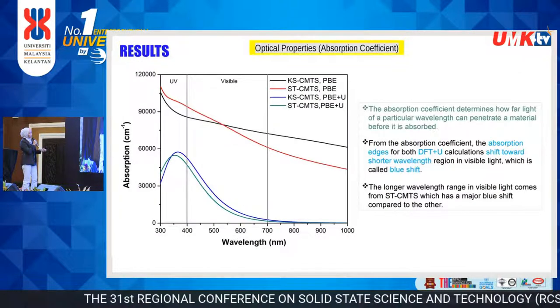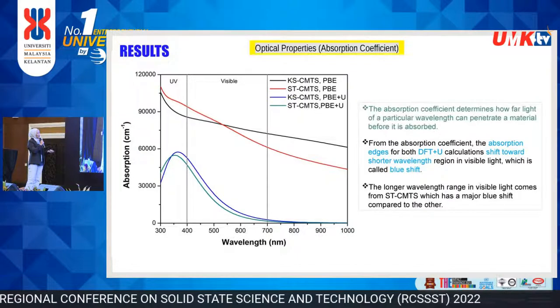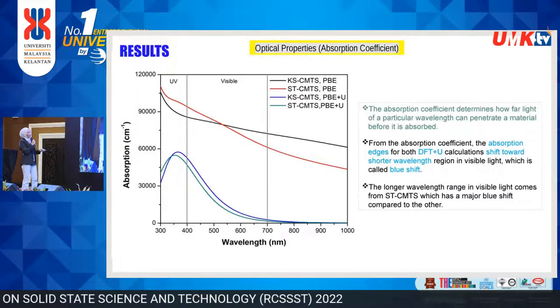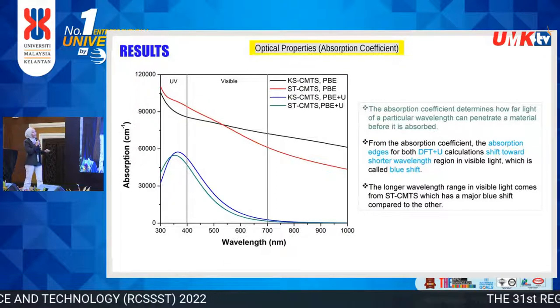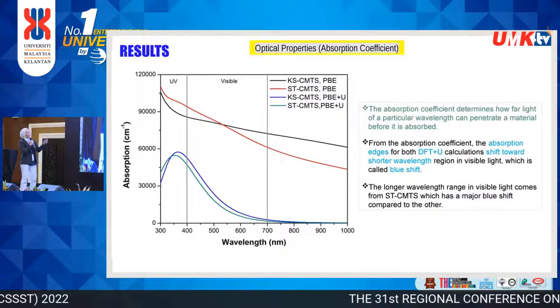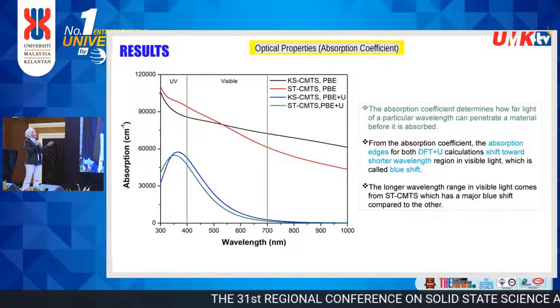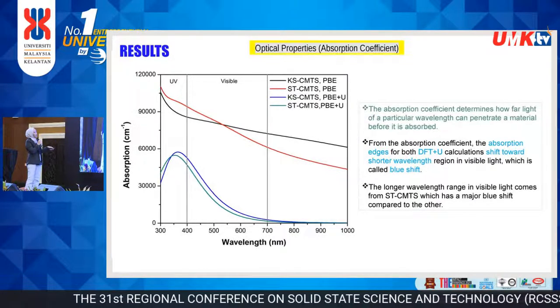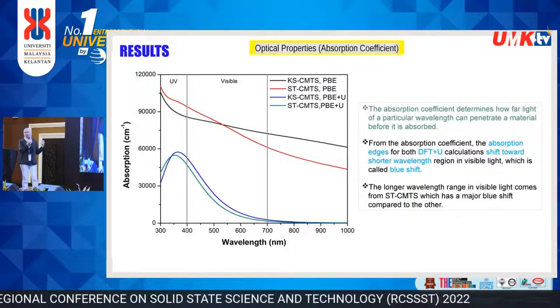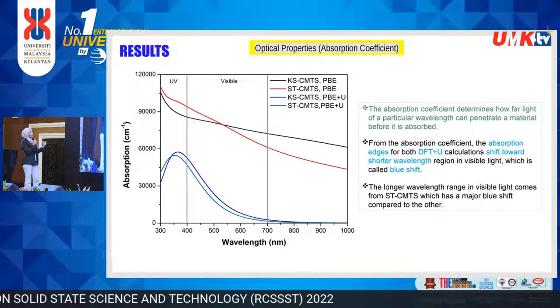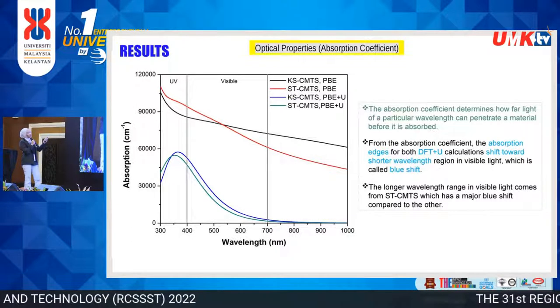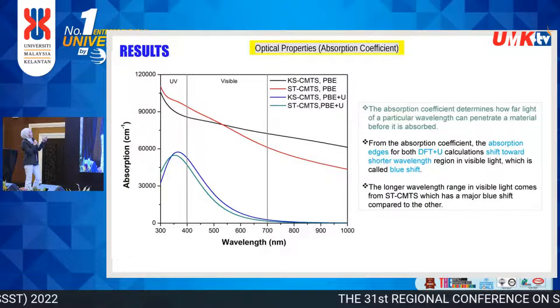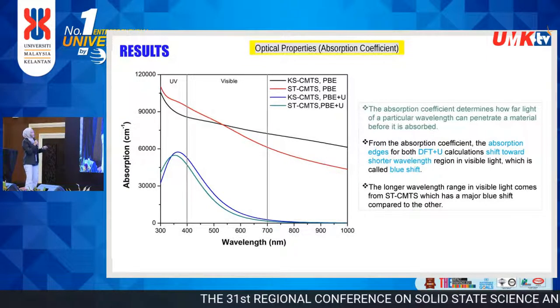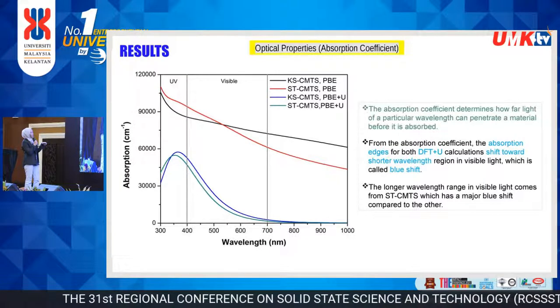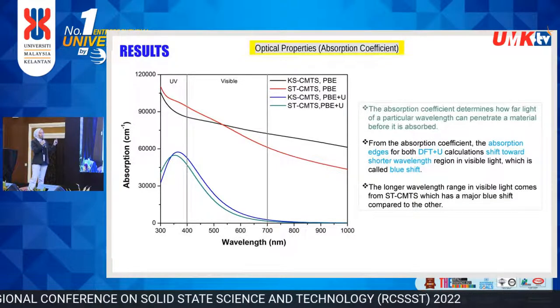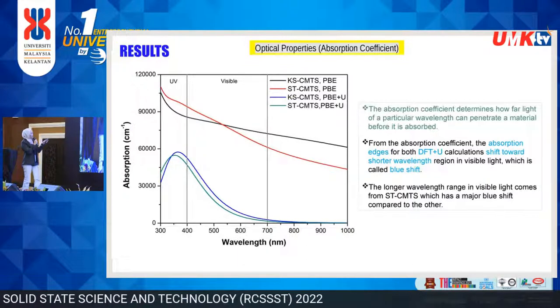Okay, this is the absorption coefficient, which determines how far light of a particular wavelength can penetrate a material before it is absorbed. From the absorption coefficient, the absorption edge for both DFT plus U, the blue color and the green color, shifts toward the shorter wavelength region in the visible light, which is called blue shift, while the longer wavelength range in the visible light comes from the standard CMTS, the red color one. However, all the materials here have a high absorption coefficient, up to 10 power of 4 cm negative 1.